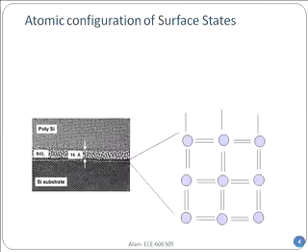Anytime you pull the silicon up, the silicon that was terminating, providing an electron and participating in the double bonding, will take its electron out. If it takes its electrons out, then the remaining silicon atoms on the surface are in trouble, because they no longer have the 4 electrons from the neighbors that were necessary to complete the bond. Each one of them is then deficient by 1 electron, right? These are called dangling bonds. The atom itself is not dangling. It is fine on its own, but it is waiting for another electron to come along.